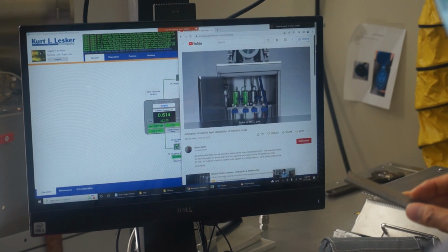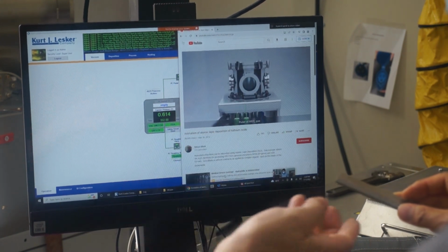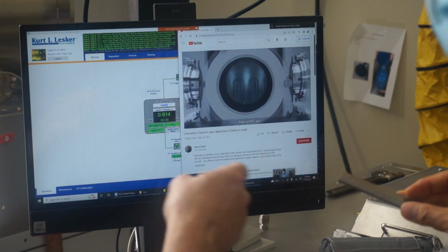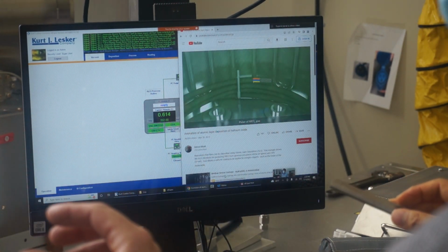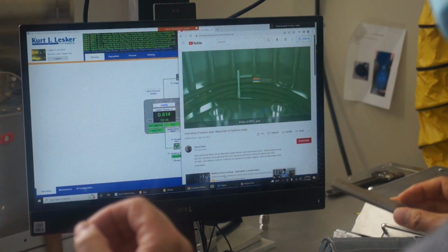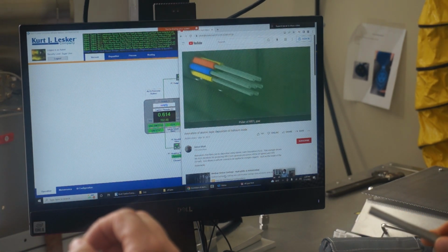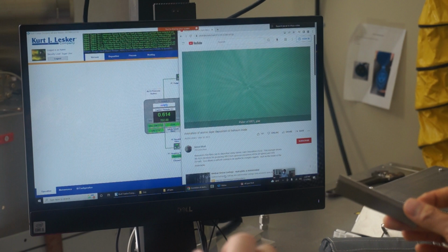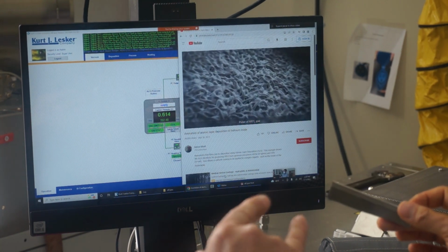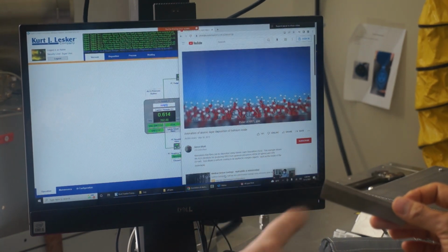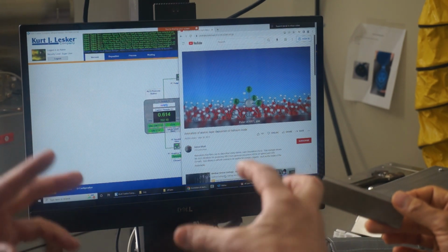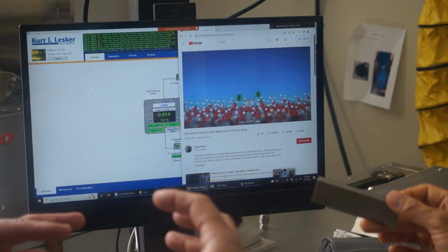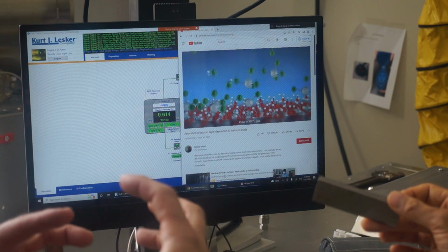And this way, instead of using the substrate heater to heat your sample, you're using the reactor as an oven. You don't have very direct heat transfer by conduction because you're not touching so much, but you have a whole lot of heat transfer via radiation because of the oven.